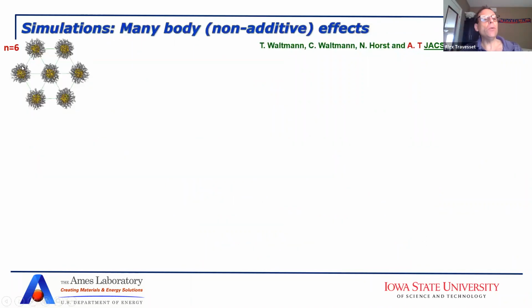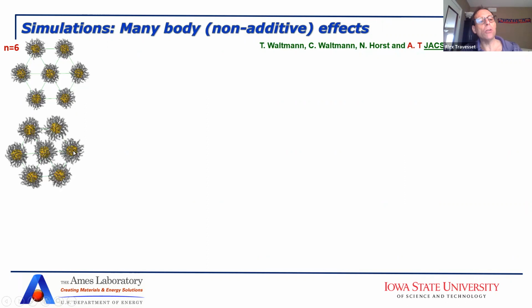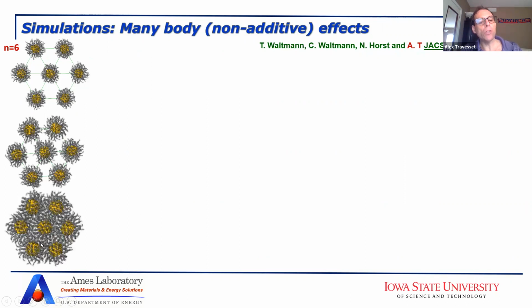So one of the calculations that we've done is, for example, the characterization of many-body effects. Many-body effects is, for example, a situation like this, where you take 6 nanoparticles around 1 particle. So you have a coordination number 6 nanoparticle, the one at the center, and then you approach the nanoparticles closer and closer, and you compute the free energy as you approach them. Then you compare the free energy of the system with the free energy of the particles interacting as a pair potential, that is, through the potential of mean force.